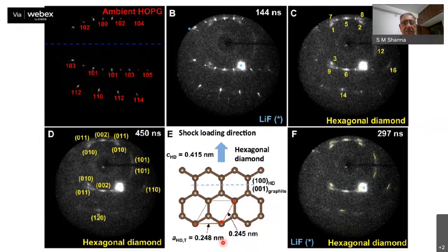See, the recovered samples earlier, either in the early shock experiments of De Carli and Jamieson, or what was recovered in the meteoritic sites, the recovered actually means they were subjected to the rising edge of the shock wave, and then the steady part of the shock wave, and then the release wave. So it has the whole pressure-time history to which graphite has been subjected.